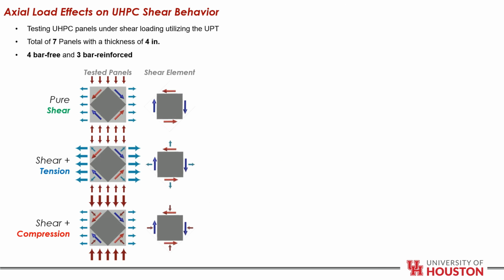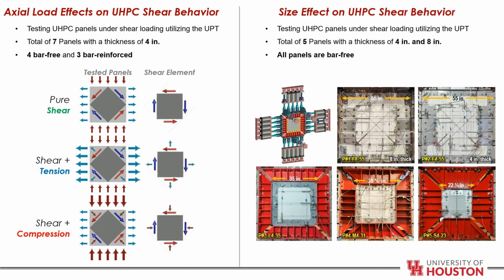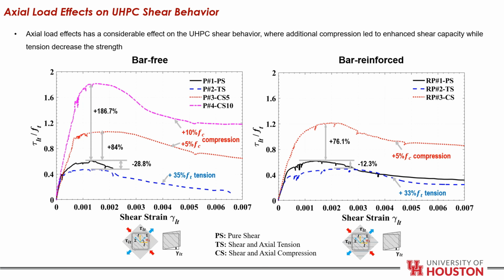The test matrix consisted of a total of 7 panels under pure shear, shear with tension, and shear with compression. On the other hand, the size effect study was conducted utilizing a total of 5 panels, all 4 inches thick except the first panel, which is 8 inches thick. The results showed that additional compression and tensile loads highly influence the shear response of UHPC, as we can see, increasing the compression force by 5% of the compressive strength increased.